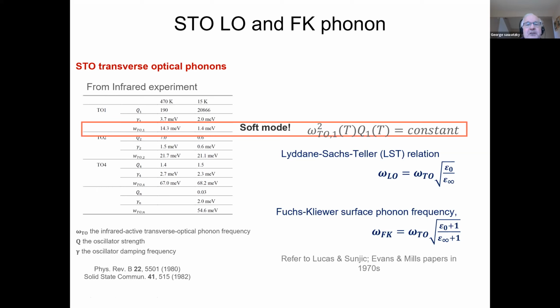However, there is no temperature dependence actually seen in these photoemission or in the intensity or in the electron energy loss spectrum. And that's because there's a rule that omega squared times Q is a constant. Okay, so we get rid of that first, okay? So this is the transverse optical phonon, and you know from the Lyddane-Sachs-Teller relationship that the longitudinal optical phonon is the transverse one times the square root of epsilon naught divided by epsilon infinity. And the Fuchs-Kliewer surface phonon frequency is just the same thing, except you add a 1 because it's a surface effect. The vacuum has a dielectric constant of 1, epsilon naught plus 1, and epsilon infinity plus 1. And you can work out this theory perfectly, and you get beautifully all of these transverse phonons yielding the Fuchs-Kliewer phonon that you see in electron energy loss spectroscopy.